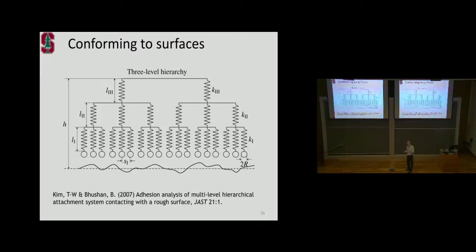So what happens when I pull? Well, when these ones are actually going to have a higher stress on them, they will fail first. And then, this goes back to the crack thing, it's a crack propagation problem. As soon as you get a little bit of peeling initiated anywhere on your adhesive surface, it's like an avalanche. It just propagates across the whole area. So you need to find a way to suppress that from happening. Well, think about that. How could we ensure a more even loading across a large area and suppress this kind of stress concentration failure mode, which is the bane of all adhesives?